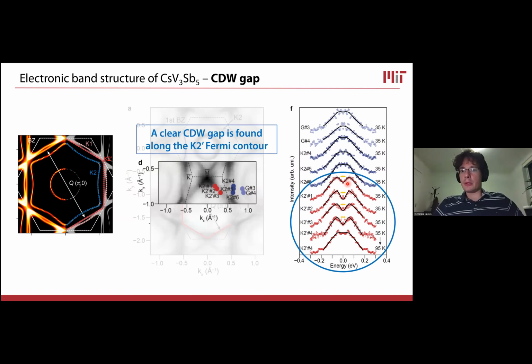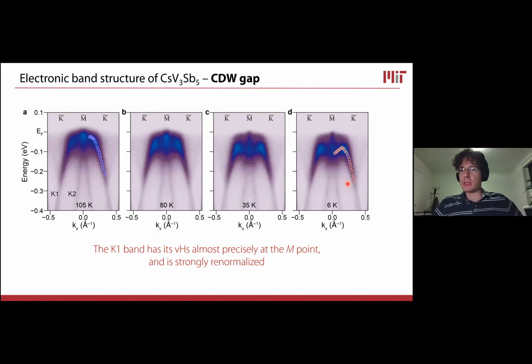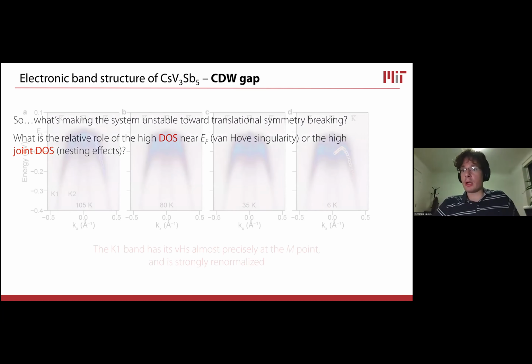But the real large gap that we see in the experimental dispersion is the one that involves the K1 band, which is a different band that also has a Van Hove singularity very close to the M point. You see it right here, where the dispersion becomes locally flat for this band, going from K to M back to K. And then as we enter the charge density wave phase, and we go all the way to low temperature at 6 Kelvin, we see a massive renormalization of the dispersion of this band by as much as 80 millielectron volts, which means that essentially 2Δ over k_BT is of order 10. So, potentially we're looking at something which is very strong coupling.